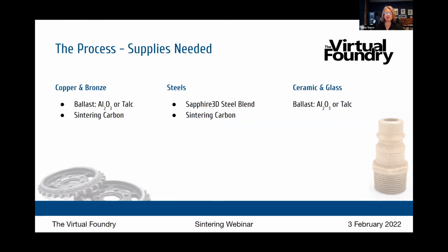Copper and bronze, you're going to use an Al2O3 or a talc and sintering carbon. Steels, that ballast material is going to be the Sapphire 3D steel blend and sintering carbon for the oxygen. For ceramic and glass, you'll just need that ballast material, the Al2O3 or the talc. So Brad, talk to us about the difference between the Al2O3 and the talc, both of which we offer as your sintering supplies. So the Al2O3 is large particles, so it's about 100 mesh.